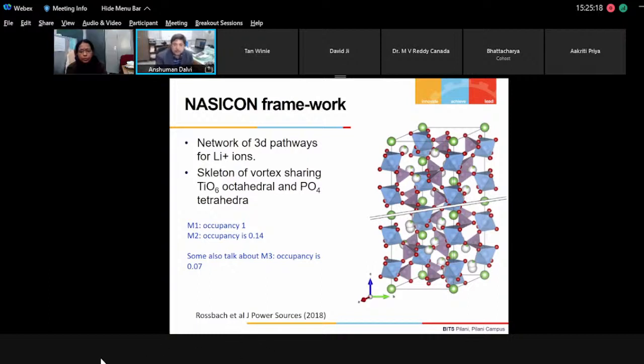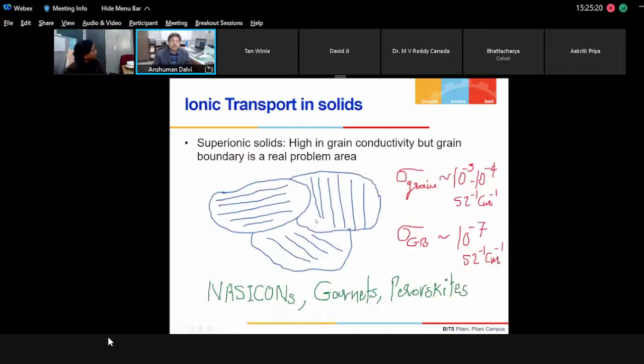takes place. So one talks about the ionic conduction, then inside the grain, ionic conductivity is as high as 10 to the minus 3 ohm inverse centimeter inverse in many of these materials, particularly garnets and NASICONs. But when you talk about long range ionic motion, then the grain boundaries create trouble, and grain boundaries offer a lot of impedance. High grain boundary impedance leads to the conductivity dropping by a few orders of magnitude. So the total conductivity is not sufficient in that case for the purpose of the devices.